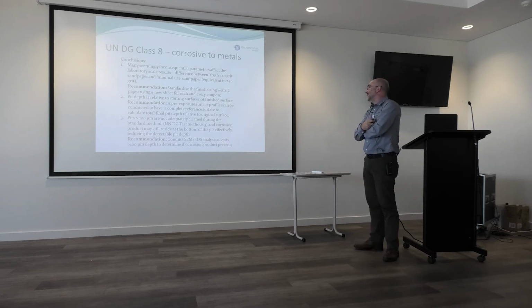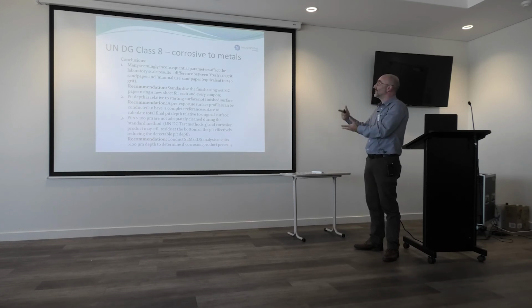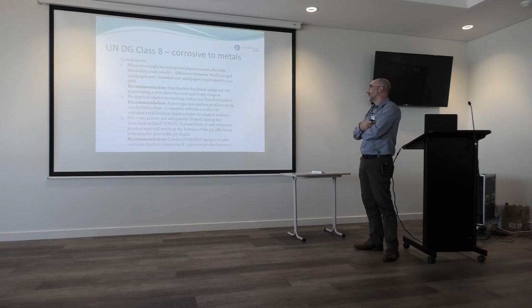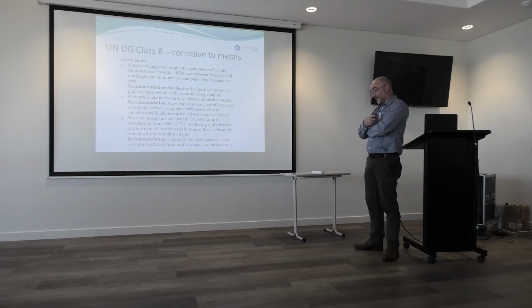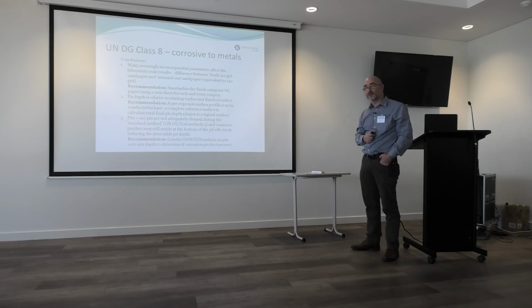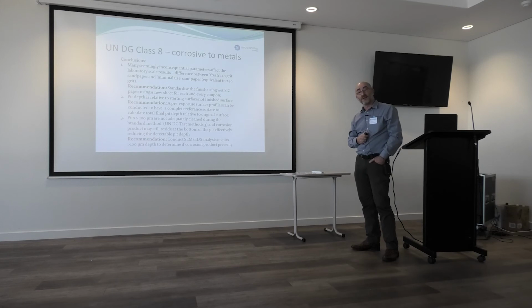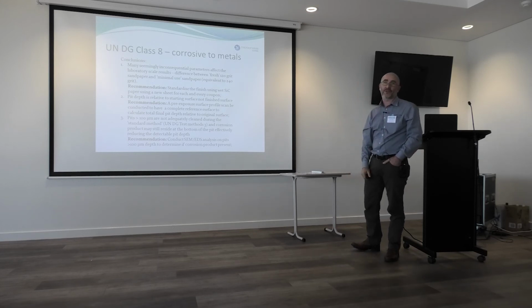So the pit depth, we tried to put forward the issues that we were having with actually understanding the pit depth relative to the starting surface, and also getting a pre-surface scan if there were any defects from the rolling process. A lot of the coupons that we were analysing actually had defects in them as deep as 20 to 30 microns from the rolling process, so they could actually then turn into a corrosion pit during the test. So if you're going to fail something on a 120 micron pit, well, it was already 20 micron before the test started.